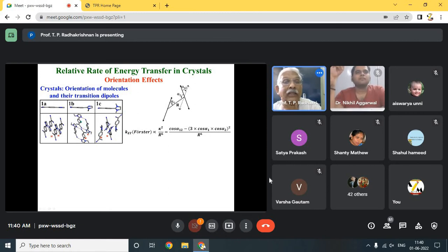interesting things. Here the molecules are very close because of some hydrogen bonding and they are pretty flat and almost packed nicely. Here, because the molecules are more twisted, they cannot pack so well, they become almost orthogonal. These two molecules, if you look at, are very orthogonal. These two are quite far apart. That means the distance becomes far and the dihedral angles, the angle between the molecules, will become also very highly modified.